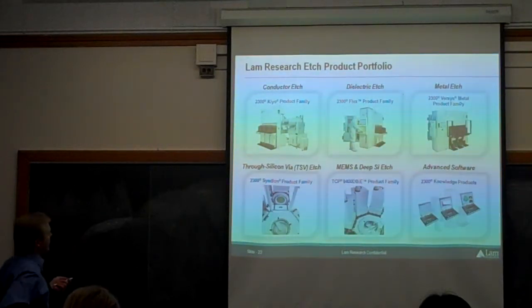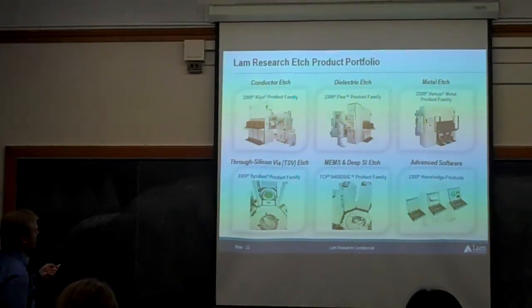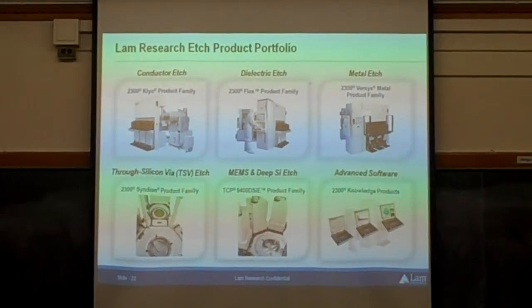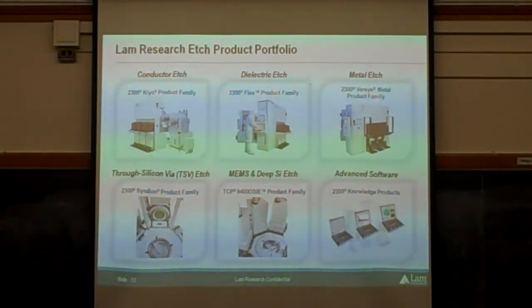So if I look at what are the products that we have in the etch series, again, that little schematic that I showed would be sitting right here. That's what this box is enclosing. Underneath is where the pumps are, and the top is where the radio frequency generators are. And we basically have to design different types of plasma technology to etch different types of materials. So this etches things that are conductive typically, so silicon, but not metallic conductive, the semiconductor conducting materials, so primarily different forms of silicon. This will etch dielectrics, so the oxides and the nitrides that are used as insulators, and this will etch, typically, aluminum. The copper, it turns out you can't etch.